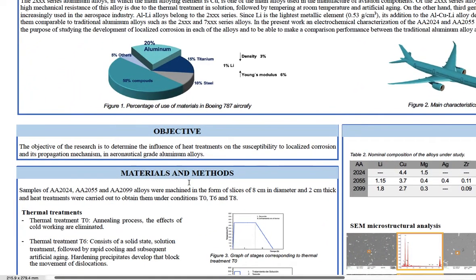In this work, an investigation was carried out on the corrosion performance of two types of alloys: the 2024 alloy, traditional in aeronautical application, and the aluminum lithium alloys 2055 and 2099, which are relatively recent. These alloys, subjected to three different thermal treatments, were tested in the presence of three different electrolytes. So, the objective of the work is to determine the influence of heat treatment on the susceptibility to localized corrosion and its propagation mechanisms in aeronautical grade aluminum alloys.